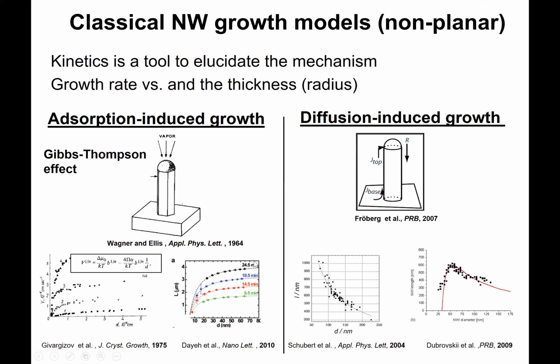In the early days of nanowire growth, in the 60s and 70s, most of the observations were that the nanowire growth rate increased with the size of the catalyst. And this was attributed to the fact that...